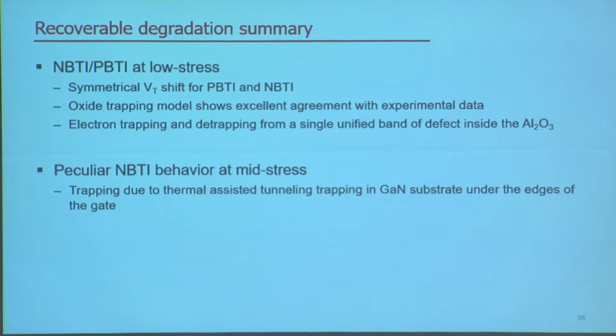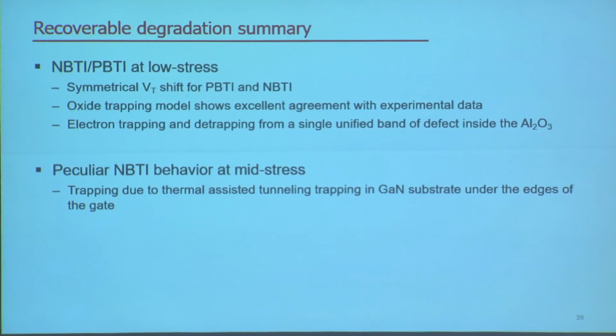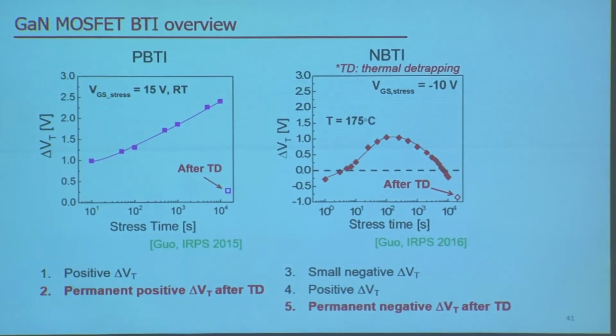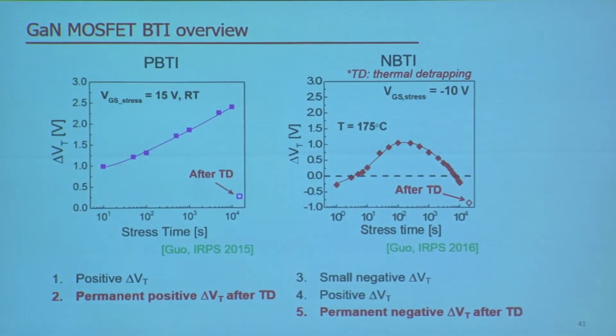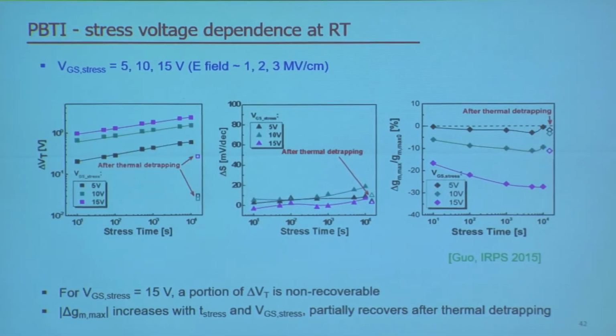And we also look at the very peculiar NBTI behavior at mid-stress, where we see a positive VT shift, and that is due to the trapping in the gallium nitride substrate at the edges of the gate. Next, I'll move on to the permanent degradation part due to BTI. And so we have covered regime 1, 3, and 4, and now I will talk about 2 and 5. And I'll start from PBTI.